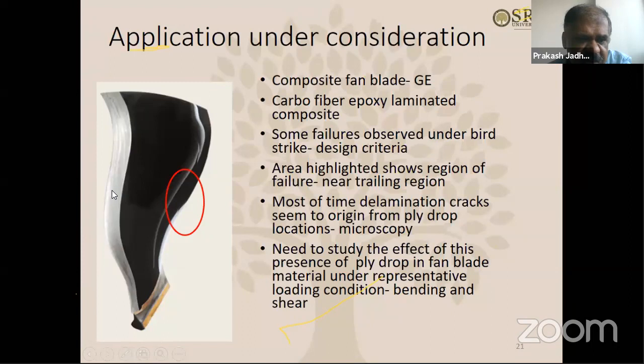So when the bird comes and hits this leading edge, the blade bends in all directions, lengthwise and widthwise, and sometimes cracks are initiated, and the cracks propagate to failure. So where do they initiate? Are they initiating at the ply drops or somewhere else? That is what we need to find out, and that's what the study is about. Most of the delamination cracks seem to originate from the ply drop locations, as the microscopic picture shows. We need to study the effect of the presence of ply drops in the fan blade material under representative loading conditions like bending and shear.